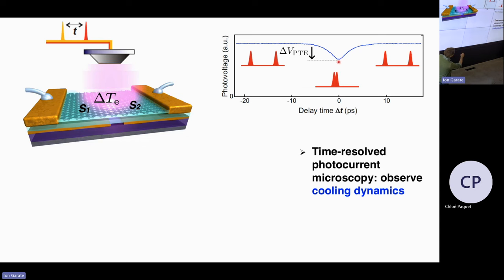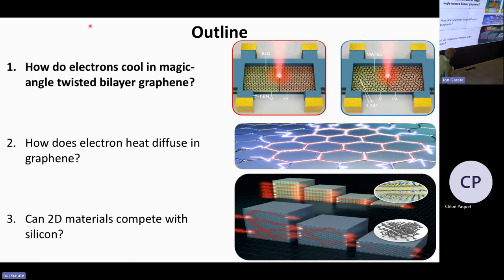Now, what's interesting is that the recovery of this signal, from the slightly smaller signal to the slightly larger signal, is actually proportional to, or reflecting, the actual dynamics of your system. So you can see here these cooling dynamics of the system as a function of delay between these two pump pulses. So you have access to the cooling dynamics of the system. Now that's going to be very interesting for this first part of the talk, which is how electrons cool in magic angle twisted bilayer graphene.